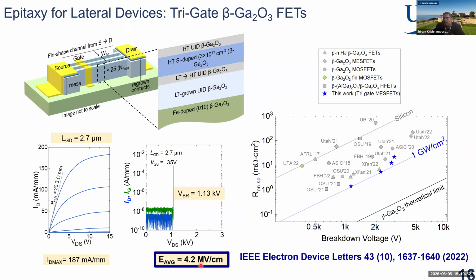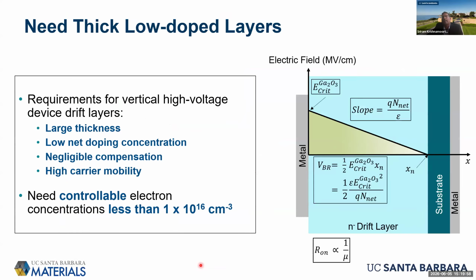But these lateral topologies are okay for lower voltages. Eventually, we need to get to low doped thick epitaxial layers. So we need large thickness to be able to block higher voltages, and that would then necessitate high purity material, because we need the doping to be less than 10 to the 16. If you have a triangular electric field profile, then you need sufficiently low doping and high thickness of the drift layer to maximize the area under this electric field curve, right? Which is basically the blocking voltage.